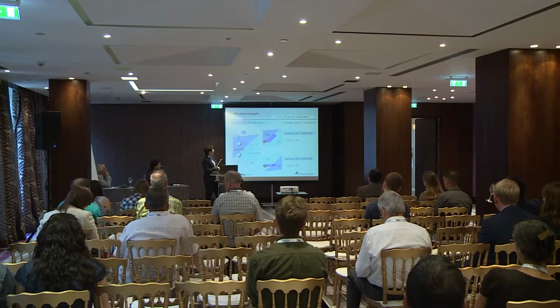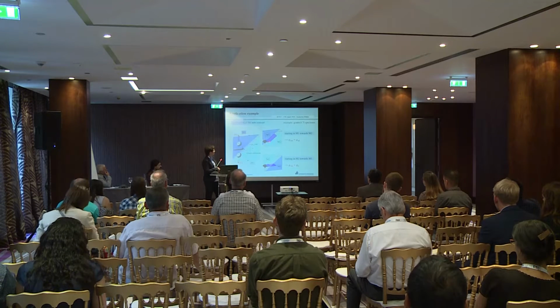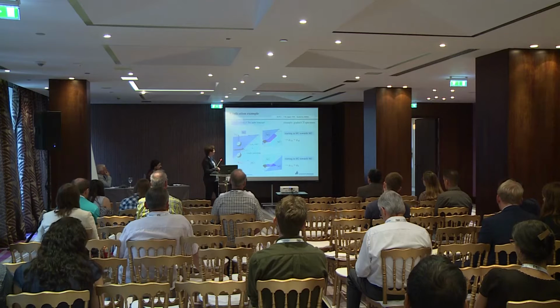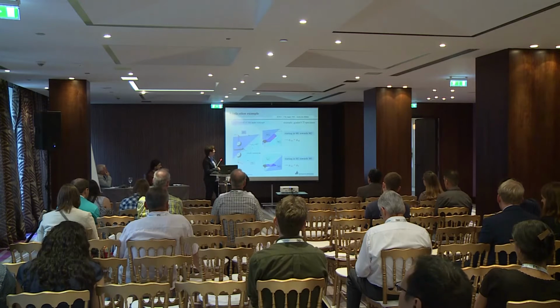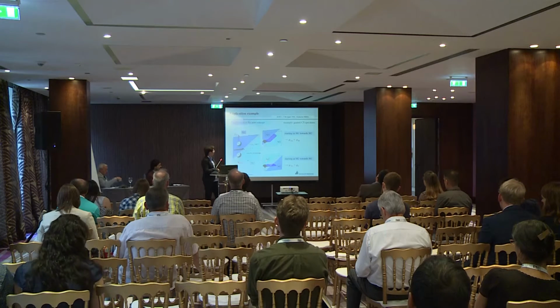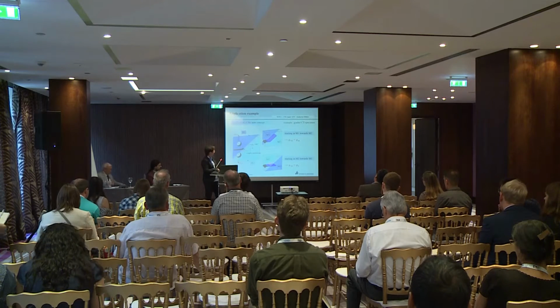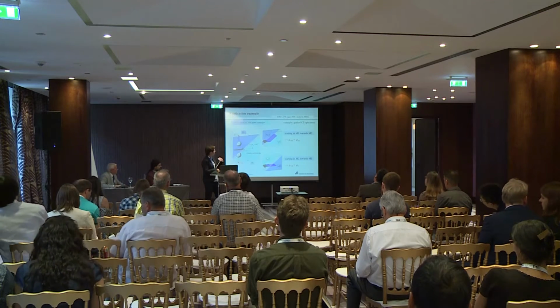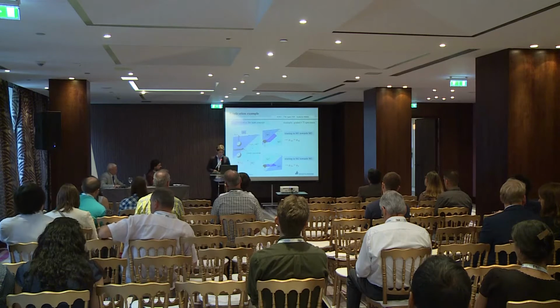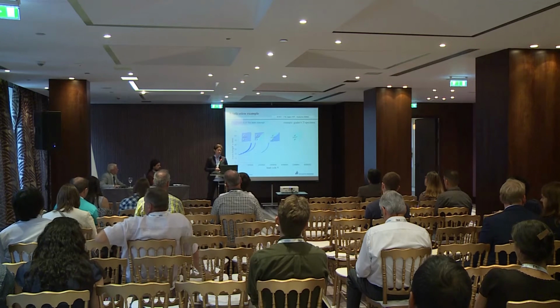When I start in my unfavorable area, as soon as the crack grows and reaches my transition, it happens that the crack will change the kinking angle and will grow along this transition. But if I change the area now, so starting in the favorable area, then the crack will just grow through it and not mind it at all. But that's only how it seems to be.